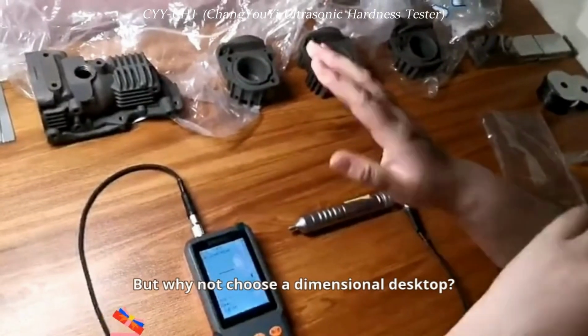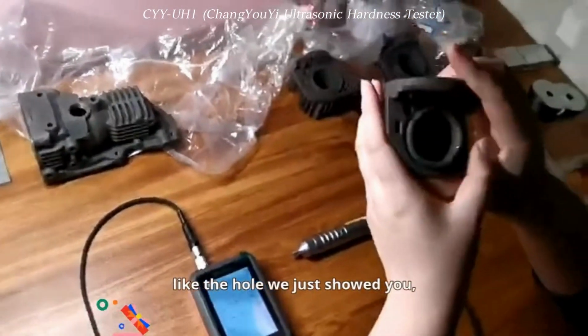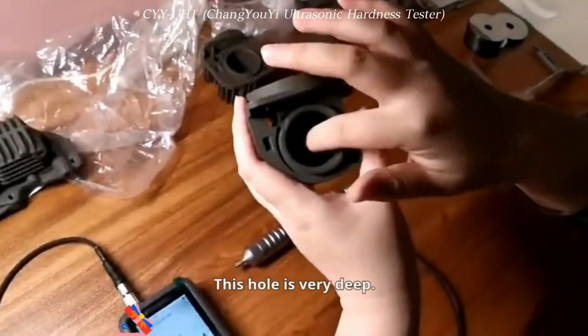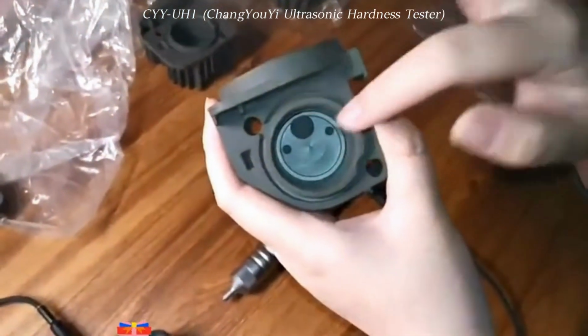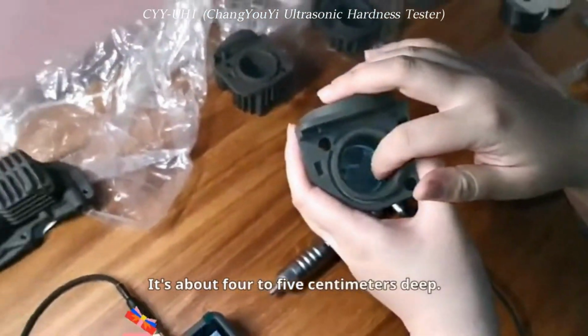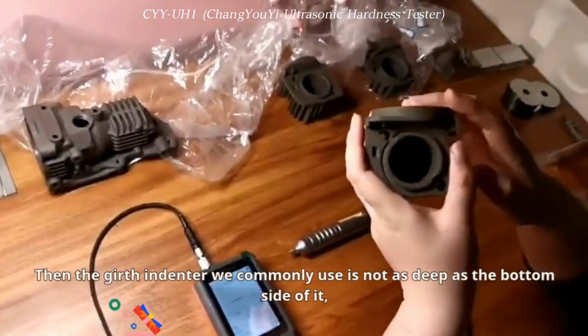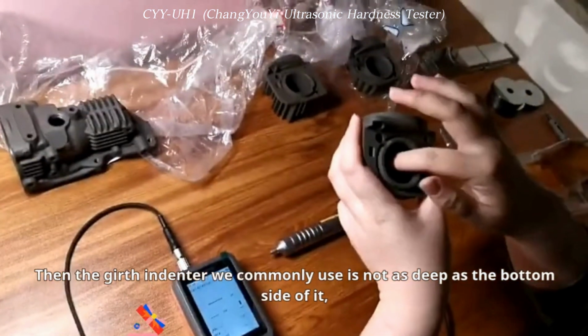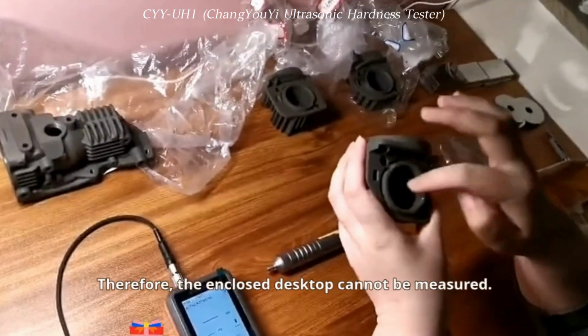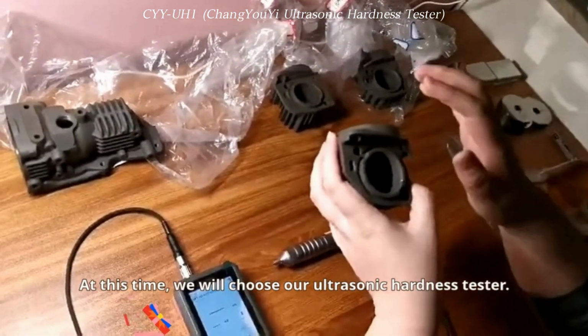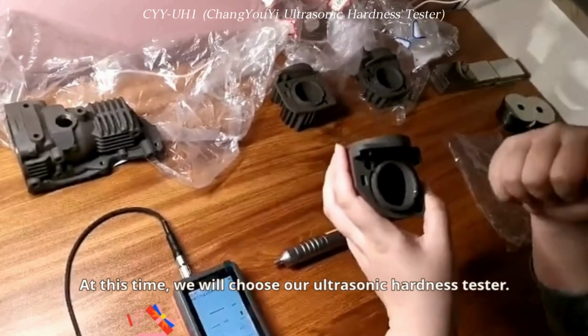But why not choose a desktop one? Like the hole we just showed you. This hole is very deep, about 4 to 5 centimeters deep. The indenter we commonly use on the desktop cannot reach the bottom. Therefore, the desktop tester cannot measure it. At this time, we will choose our ultrasonic hardness tester.